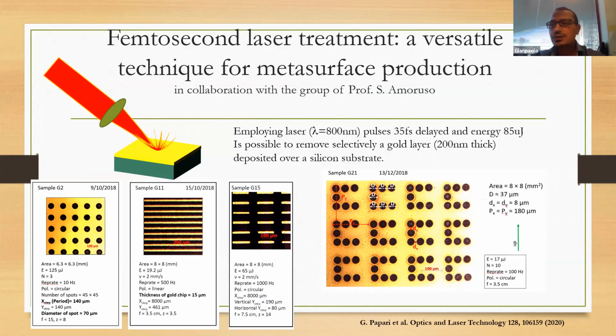But we also want a procedure to realize these metasurfaces fast, because we now have a great experience with simulators, which are very reliable. So if we provide a simulation, we are sure that the real metasurfaces will respond in the same way. Here we propose a couple of techniques, always based on femtosecond laser ablation, with structures made in collaboration with the group of Professor Amoruso. With femtosecond laser ablation, we have realized several metasurfaces and also complementary ones. Here we can see a few examples in the scale of tens of microns, which is the right periodicity for our goals.